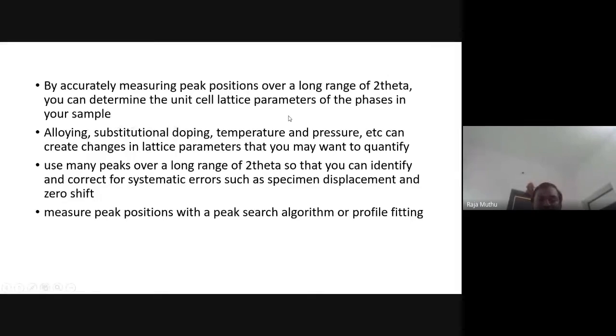Use many peaks over a long range of 2 theta so that you can identify and correct the systematic errors such as the specimen displacement and the zero shift, right? So take the maximum possible 2 theta so that we can get error-free results. Measure peak positions with the peak search algorithm or profile fitting.